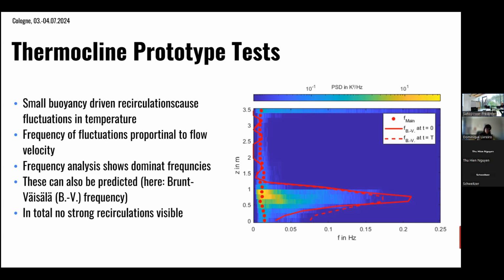And there's a theory behind this, called the Brunt-Väisälä frequency, which is linked to the flow velocity of these tiny fluctuations. From this frequency analysis, alongside the model behind it, you can then derive some sort of microscopic fluctuations. But we didn't see any large-scale recirculation, where salt is cooling down near the tank walls and then causing huge wakes of flow. So it was only on the micro scale, and in a large scale system, it's also less relevant.